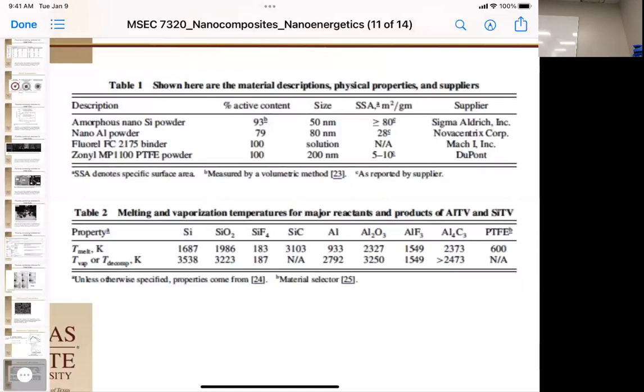But if you look at aluminum here, it actually melts lower, so it's easier to initiate. But its oxides are the same as the silicon oxide. And the aluminum fluoride is above room temperature as well here. And the aluminum carbide is even higher. And then Teflon decays around 600 degrees.